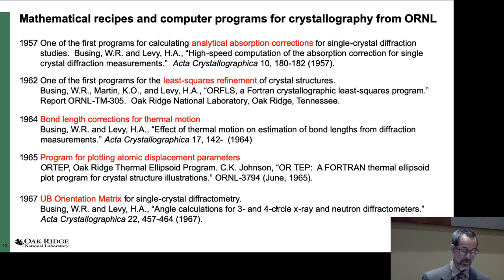Now, during this period, the crystallography group, headed by Levy, produced much of the mathematical recipes and programs that would become the basis of modern-day computer-based crystallography. There's more about this in Busing's memoir, but certainly things like the analytical absorption corrections, least squares refinement, bond length corrections for thermal motion, plotting atomic displacement parameters, and the all-important UB orientation matrix recipe were all developed first on large mainframes and then rewritten for smaller computers that were being developed at that time.